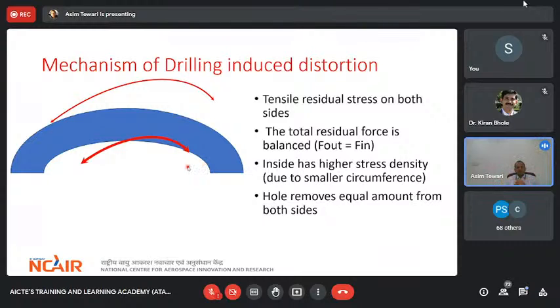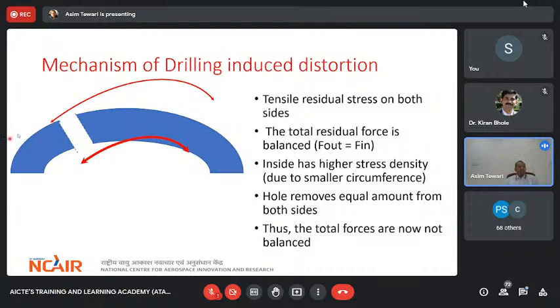Once we drill holes, a hole is essentially a constant diameter region going from outside to inside. So the hole removes an equal amount from both inside and outside. Now this is the hole. Once the hole comes in like that, the total force is now unbalanced. Why? Because you have removed the same amount of material from outside as from inside, but the inside had a higher stress density. There was more stress per unit length as compared to outside.